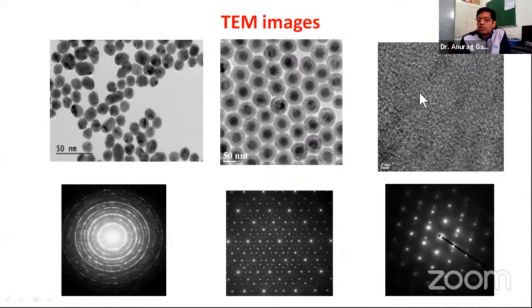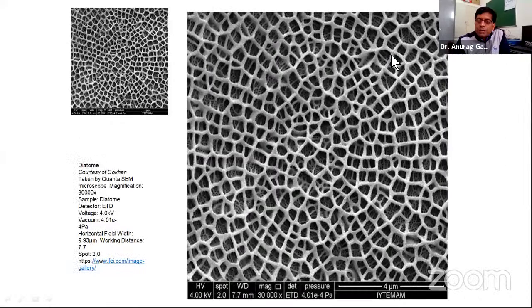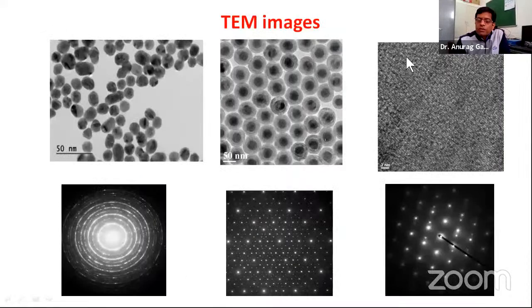This is a high resolution image of transmission electron microscopy. So basically they are atomic planes. You see these very small lines. What are they? They are the atomic planes. These are the atoms, this is one plane, and that is another plane. So you can see very, very fine particles with that. The scale bar in this image is 2 nanometer. This length is 2 nanometer.